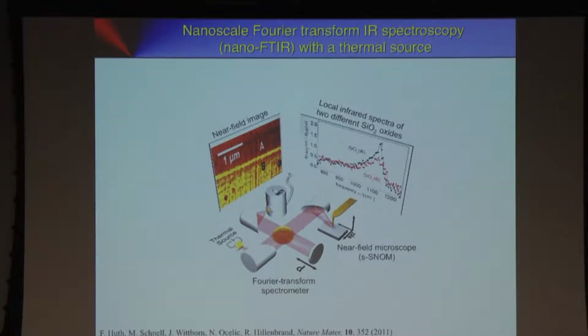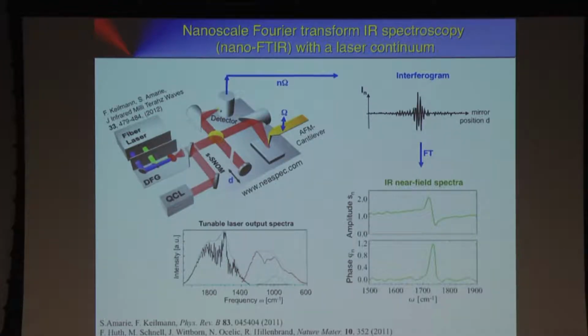And so we gave this up pretty quickly, particularly because Fritz Keilmann came up with a much better solution. Namely, based on some developments that are going on in the laser field, he set up this device here, which is a difference frequency generator. So where near-infrared supercontinuum is mixed with a telecom wavelength laser of high power in a gallium arsenide crystal, and due to difference frequency generation, a laser beam comes out here, whose output spectrum is shown here. So the spectral bandwidth of this infrared beam here is around 500 wave numbers, and it can be tuned by the laser settings and by the crystal orientation.